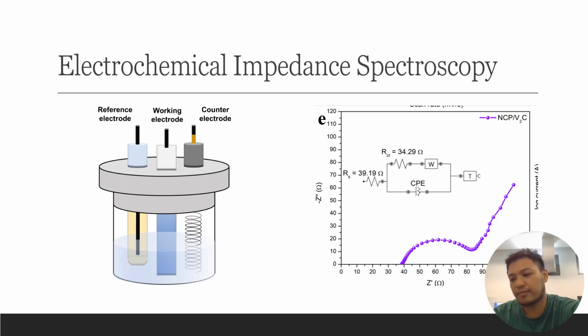Next we have the RCT, the charge transfer resistance. For the charge transfer resistance, you can see a semicircle. A circle is like a ball, so this is a semicircle, half of the circle. From the software, they will calculate the diameter of the circle. The diameter of the circle indicates the charge transfer resistance between your material and the electrolyte interface. And then we have the CPE, the constant phase element, which indicates the inhomogeneity of the electrode. When you have modified your electrode, you get a reading on the CPE value.